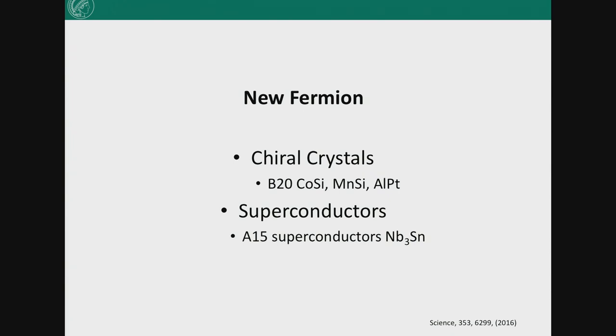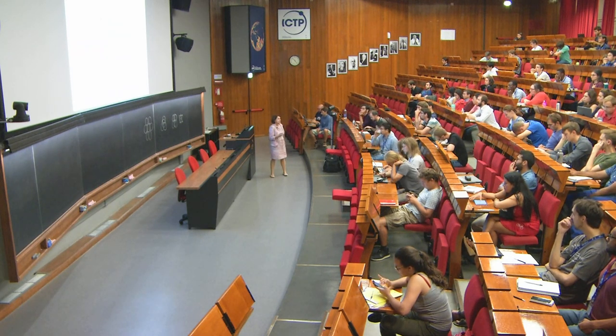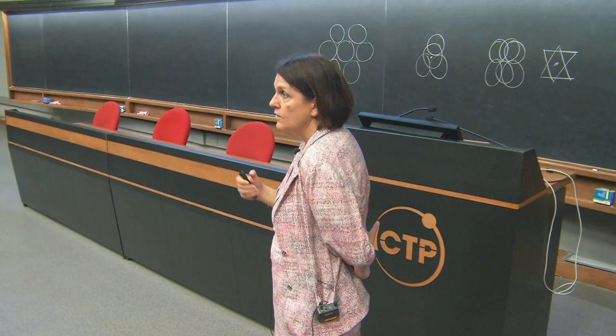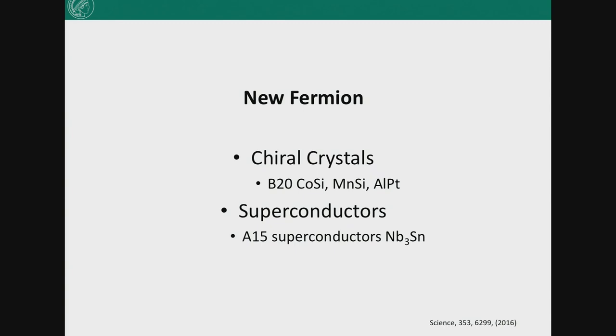And most of the crystals are superconductors, if they're not magnetic, okay? So the question is, if they're not magnetic, is there a relation between this high degeneration of the band structure and maybe that they are superconductors? One famous class of superconductors are the A15 superconductors, which are still the superconductors mostly used in application. And I think it is always luck if you have an 80 years old coworker, because he was working at the time of niobium tin, and he said at this time already people thought maybe superconductivity in these compounds was related to the highly degenerated band structures, which then, I have to say, distort slightly at the superconducting transition; there's a martensitic phase transition.